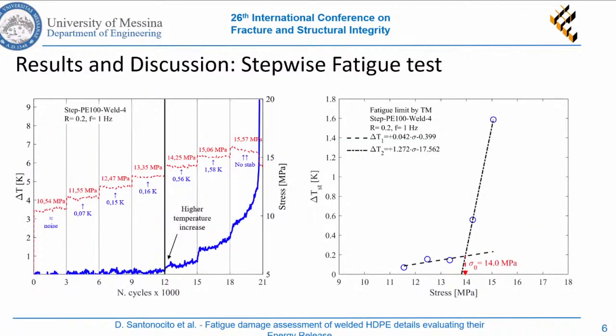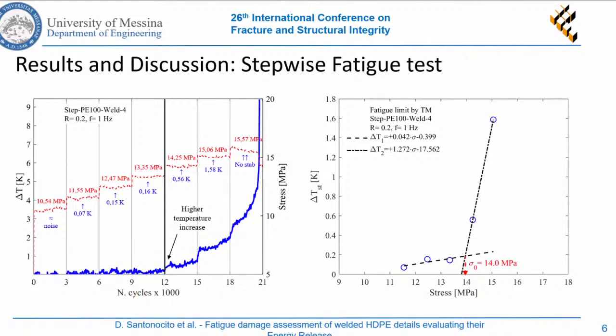Secondly, we performed stepwise fatigue tests with an increasing stress level, and we can see a higher temperature increase compared to the initial state for a stress level between 13.3 megapascal and 14 megapascal. So if we report the stabilization temperatures versus the applied stress level, and we make the linear regression of the 2 temperature trends, we can assess the fatigue limit by the thermographic method, the classical thermographic method.